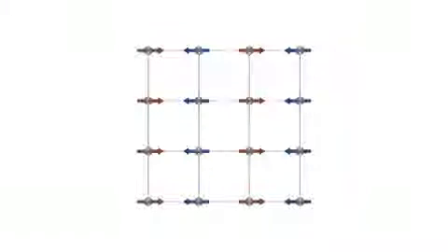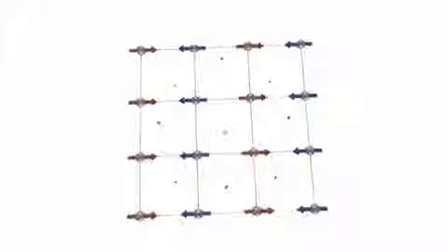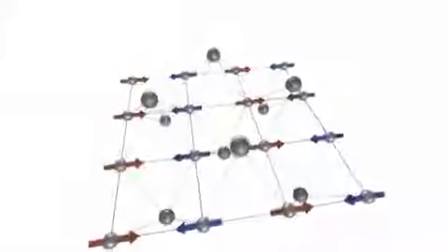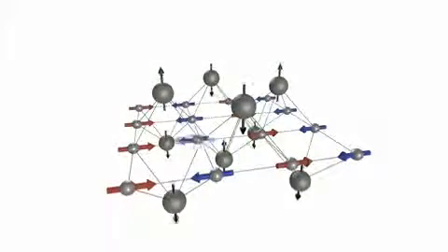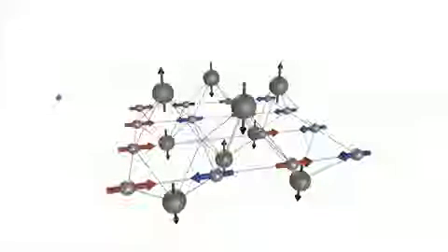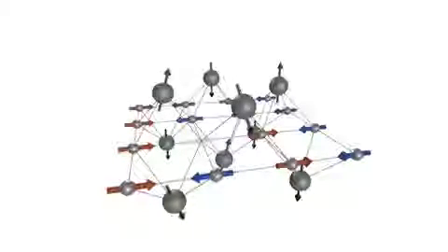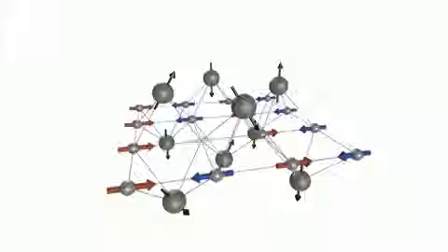In iron-based superconductors, at low temperatures, the iron atoms are magnetically ordered, which would further split the resonance signals into a 6-peak structure. Because of hyperfine coupling between arsenic nucleus and iron spins, a non-magnetic impurity could affect the local field distribution and therefore change the NMR signals.